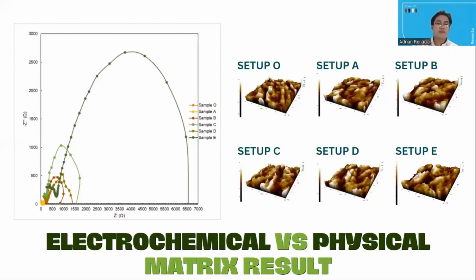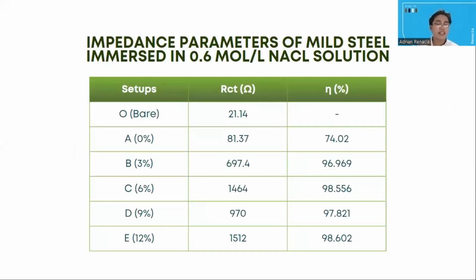The results of the experiments show that the LL extract really has the potential of being an inhibitor for preventing the corrosion of mild steel in a 0.6 molarity per liter sodium chloride environment. The obtained inhibition efficiency shows an increase with rising inhibitor concentrations. Further information about the inhibitory qualities can be gained through electrochemical impedance spectroscopy or EIS test. Since the observed rise in charge transfer resistance values denotes the creation of a protective surface film after the addition